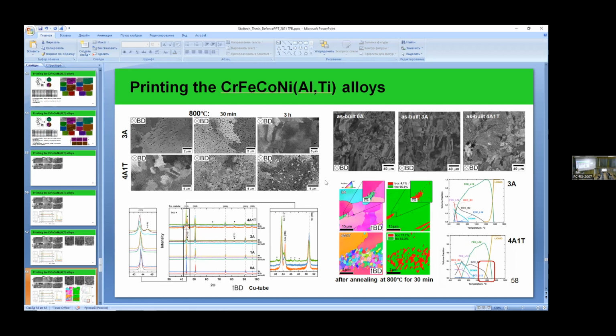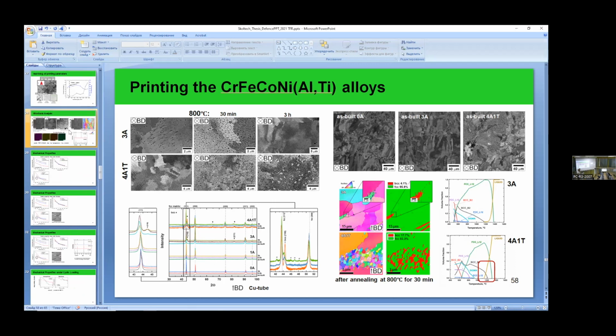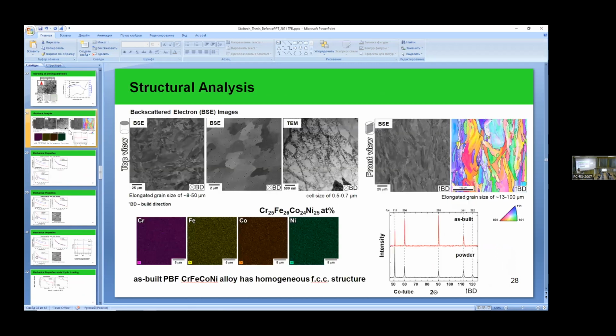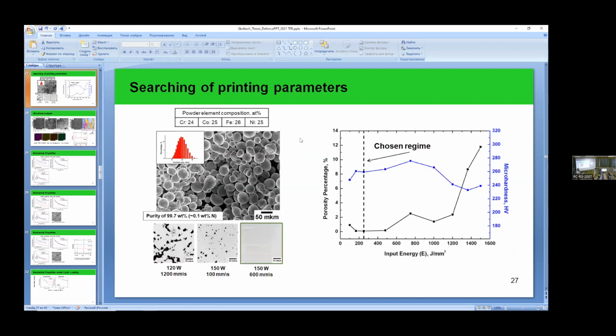I was looking at your slides. If you go to slide number 27. Yeah, this one. I observed that you have plotted porosity, input density, input energy, and microhardness. And at around 700 or 780 joules per mm squared, the data point of porosity appears to be very porous, but it also has very high hardness. So why is the hardness also high along with porosity?